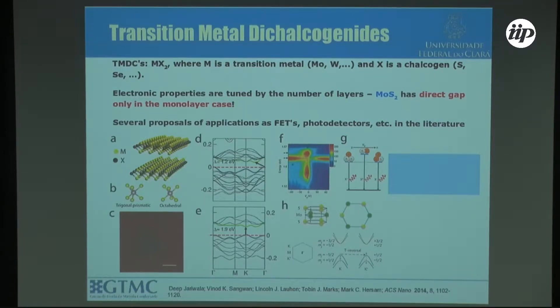In absorption experiments with these materials, if you apply a gate over the material, you can see a peak for a negative trion — an exciton with an extra charge — or a positive trion. At the neutral point you can get an exciton or a trapped exciton, so there are many things to understand in these materials. Since 2010–2013, people have been identifying which peaks correspond to which excitonic species. What I'm going to talk about here is how this exciton peak changes with magnetic fields.